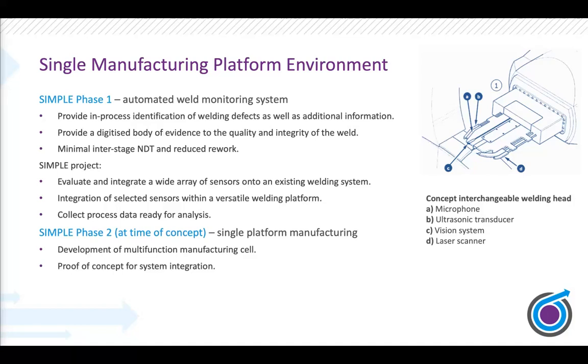So the idea behind this technology is that we establish a baseline suite of process monitoring sensors to monitor the arc and the weld as it's being deposited. Then we also have an in-process volumetric inspection technology to give an in-process check. Because of the difficulties and challenges of doing this while the material is hot and in the welding environment, you won't get a full qualified inspection, but it'll give you an indication towards whether there is anything worth flagging or whether you need to halt the process. So the whole system is giving you more process security so that you don't have to pause the process unnecessarily to do an interstage NDT. And that's how we drive up productivity, and that's how we bring down costs of these components.